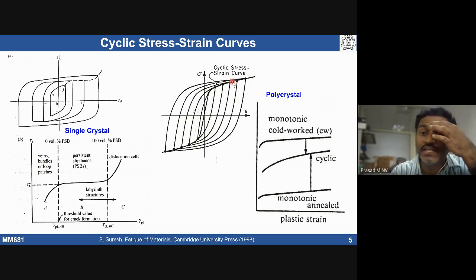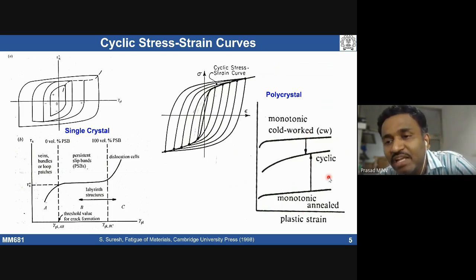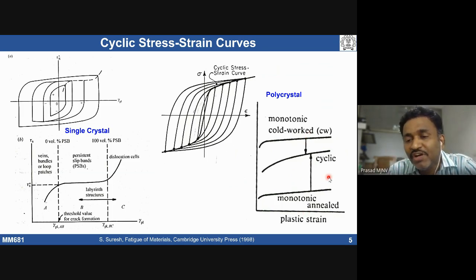Interestingly, if I take cold work material and annealed material under monotonic conditions, we see a significant difference in the stress strain curve. But if we subject these two materials separately to cyclic loading conditions, the annealed material is going to get cyclically hardened, whereas the cold work material undergoes cyclic softening. That may bring the curves together. Cyclic deformation will be different.